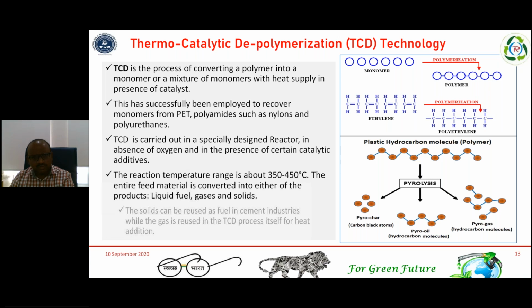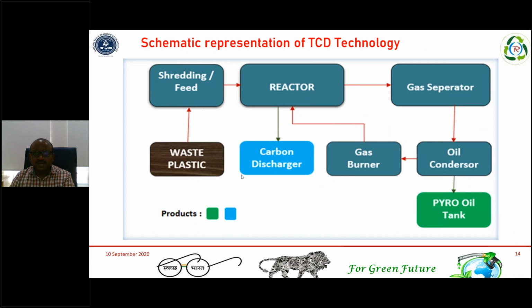In the absence of oxygen, we heat the mixed plastic waste, and we allow the temperature to reach about 350 to 450 degrees centigrade. This is the flow chart, where the plastic waste is shredded into small pieces and supplied to the reactor, where 350 to 450 degrees centigrade is maintained. From this, the vapors are collected and moisture is separated in the gas separator, and whatever vapors are condensed will be collected in the oil condenser and supplied to the pyro oil tank. Whatever gas is collected will again be supplied back to the reactor, which is useful for supplying the energy.